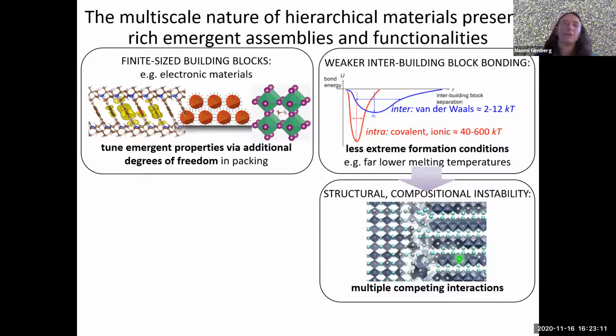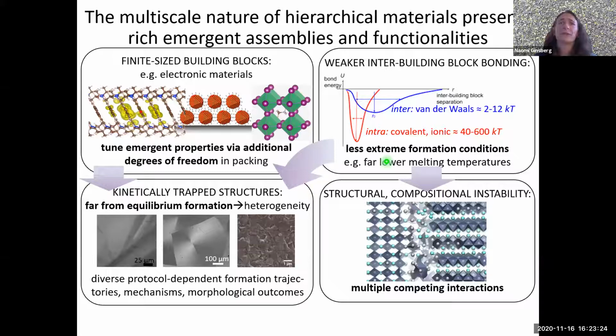And the final feature of hierarchical materials that I want to highlight is a direct consequence of both their finite sized building blocks and also the energy scales of their bonds and commensurate melting temperatures. So together, these yield dynamical pathways for material assembly or restructuring that are far more likely to occur very far from equilibrium compared to the way we grow materials with atomic building blocks. So, for example, this often means that you end up with amorphous or polycrystalline or a combination of morphologies. It can also lead to intriguing polycrystalline structures with orientational correlations, as seen in this spherulite structure here. So that makes these dynamics especially exciting to study.